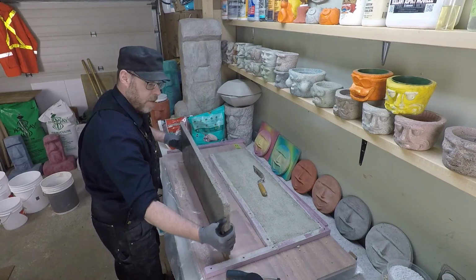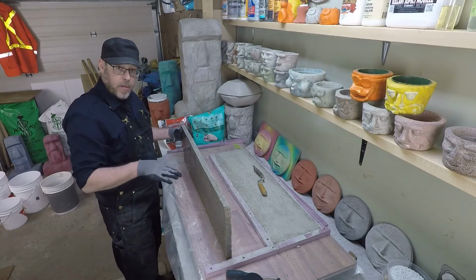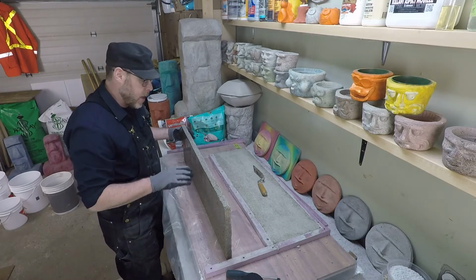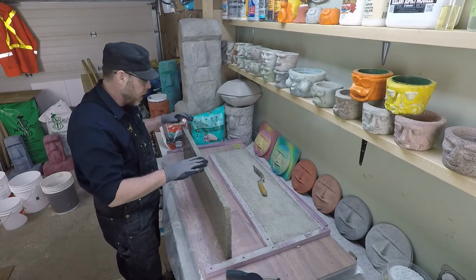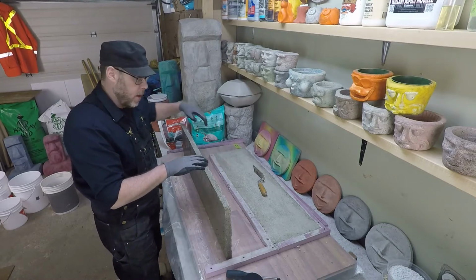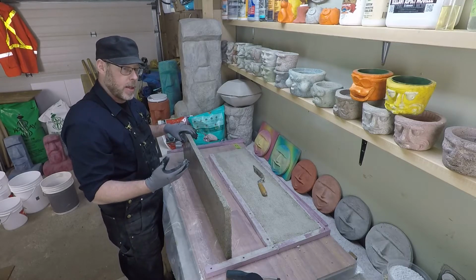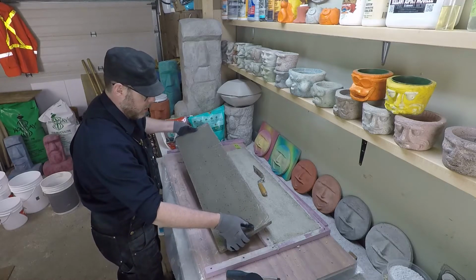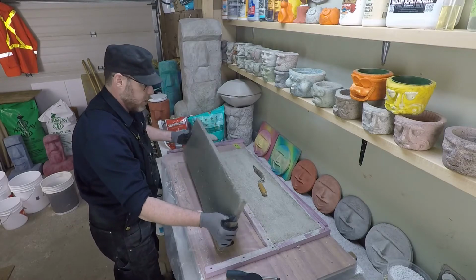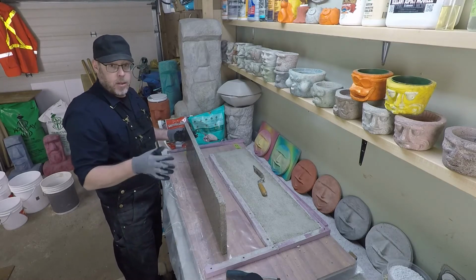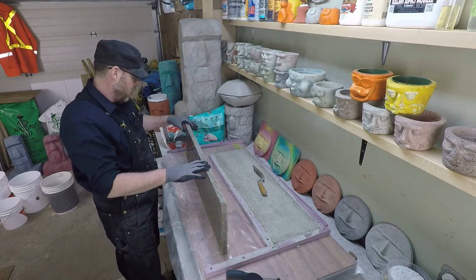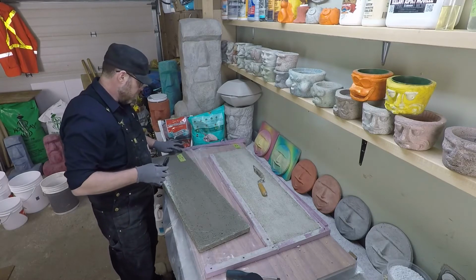You know, for a very wet mix, I would have thought I would have had better consolidation there, a good amount of honeycombing. I'll be interested to see if the dry mix is consolidated enough. If the wet mix was missing a couple spots like that, the dry mix could be much, much worse than that. Okay, this is not cured yet.